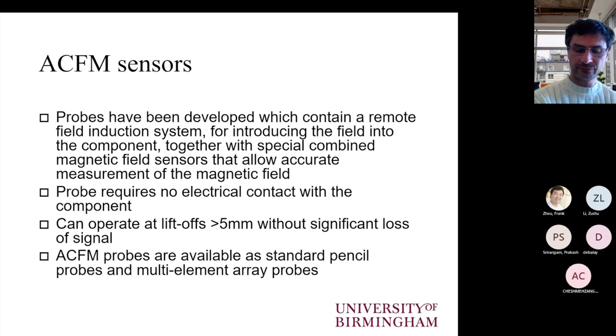In the case of ACFM, we can, of course, try to bring our probe as close as possible, but we can live with higher liftoffs, provided, like in eddy current testing and in MFL, we don't have liftoff variations, because this will result in signals that look like true defects, which are not really related to real damage. They are artifacts in the measurement.